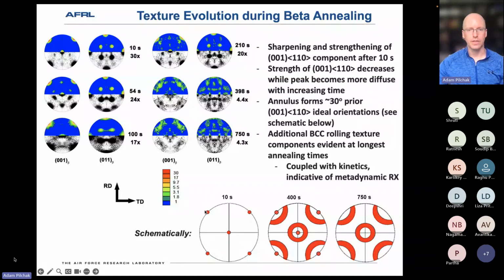Since the 100 poles on the periphery of the pole figure aren't necessarily aligned with X and Y. But the main point is, starting from this nominally single orientation here, after some amount of time, we see this kind of annular ring developing around each of the initial sharp intense 100 spots, and the intensity of the original sharp 100 texture component decreasing. And then with further annealing time, we see almost a complete transition from our original sharp texture component to only these annular rings around there.